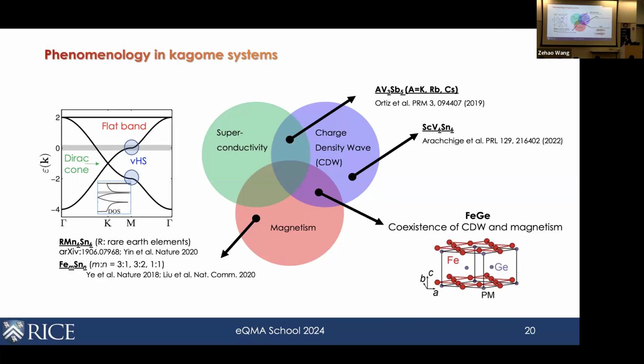So if you look at these systems, under the systems that have a magnetic order, there are 2 families. One is the so-called 166 family, and they're either manganese-based or iron-based, and they tend to have very high ordering temperatures above room temperature, in the range of 300, 400K. And then the other system is iron tin, iron germanium, so on and so forth, that also have magnetic order.